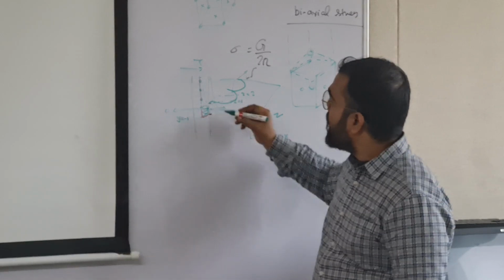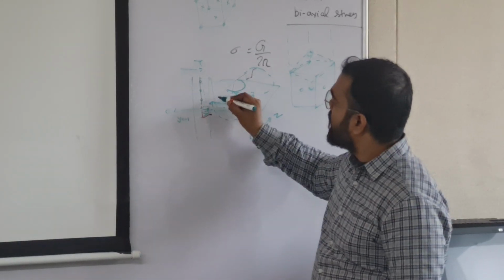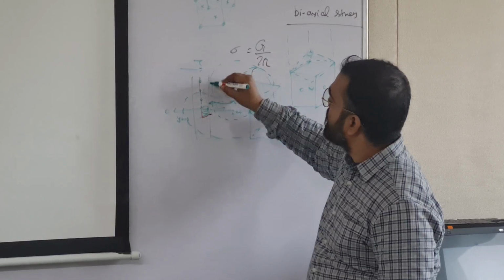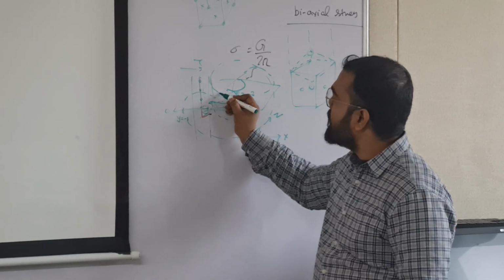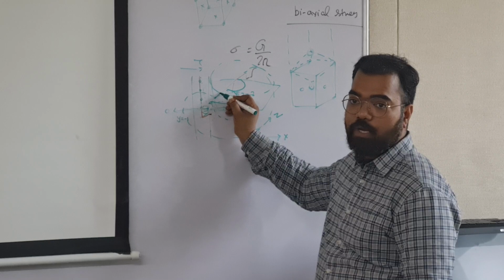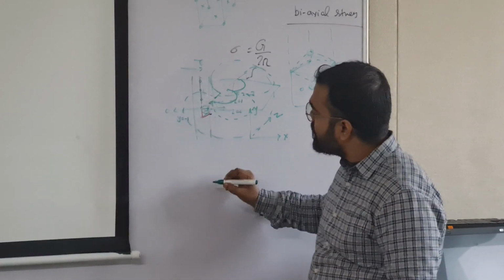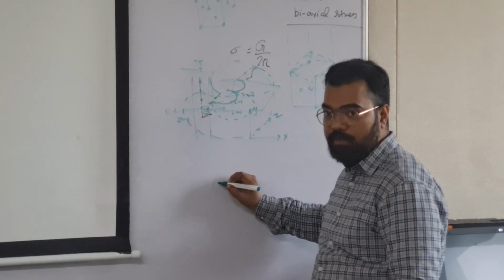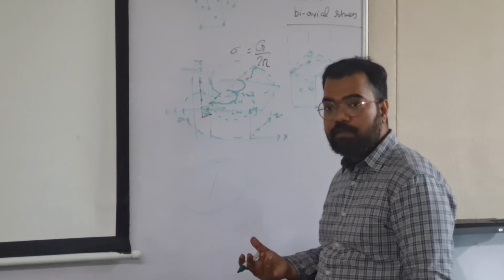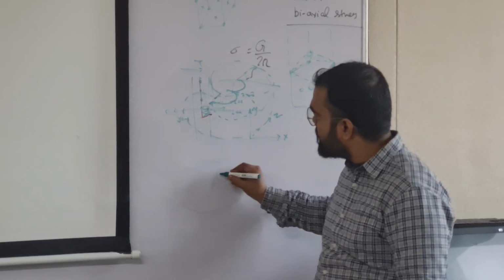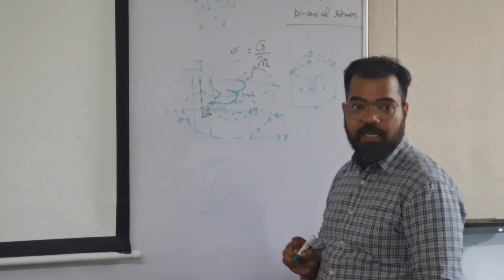And after a lot of shearing stress, it will become like this, and after a certain point, it will become like that. And the nature of these 2 points are exactly opposite, so they will merge after some point of loading. And then what will you have? You will have the original dislocation as it was, and you will have another dislocation which is created. And it will not stop there because you are still not stopping. So again this will bow out and the same phenomena will keep on happening. So what is happening now is we are creating a lot of dislocations.